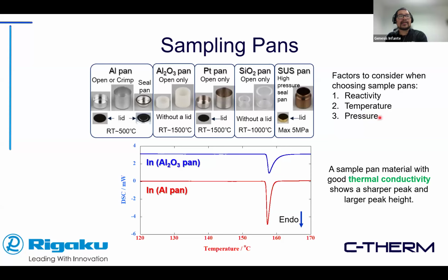And rarely, sometimes DSC studies can involve pressures. So some pans are designed to be able to contain high pressure, such as this stainless steel pan, where there's some sort of lid threads, or a certain way of sealing it. Aluminum pans, usually you can also seal them to be able to handle relatively high pressure, if there's a significant vapor pressure going on, or if you just want to test your sample under a particular pressure itself.